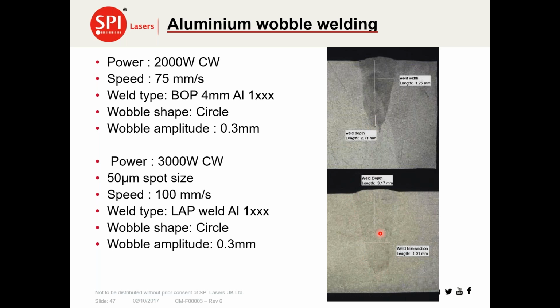Perhaps not as square as the copper, but we can extend that if the applications require. Here we've only got a wobble amplitude of a mere 300 microns. We could extend that, but that gives us something in excess of a millimeter in terms of interfacial weld area at half depth.